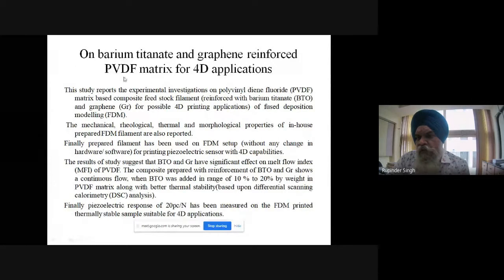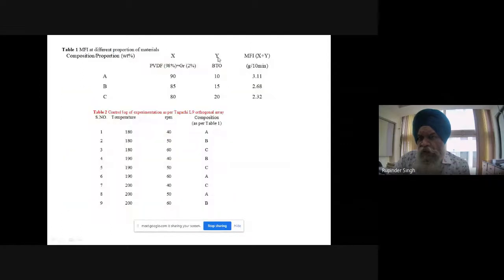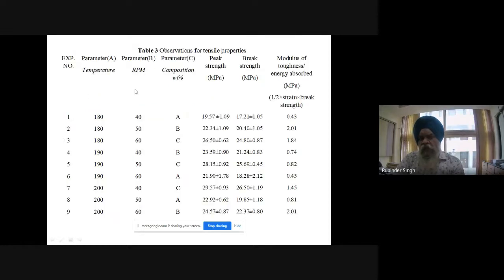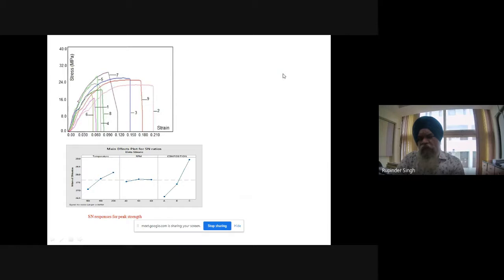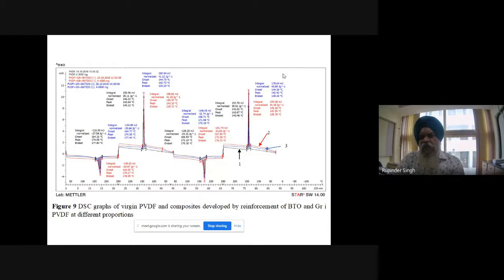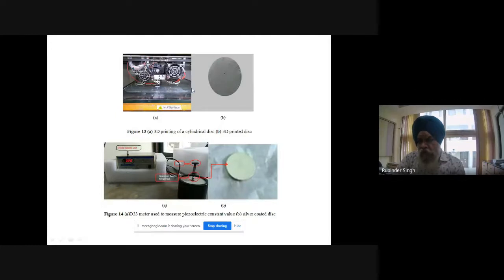We use a smart material, PVDF, and to increase its piezo property as a smart material, barium titanate and graphene were reinforced into it, right? So we tried initially with 98% PVDF, we put some graphene and some barium titanate into it. We did some parametric optimization, and we tried to see the effect on peak strength, break strength, modulus of toughness, the stress strain curves were observed, the thermal stability values were observed. Then we tried to print the component, and we tried to see what is the effect on the piezoelectric constant. So D33 was measured, and we were able to get around 20 picocoulomb per Newton. This is very good for the self-assembly application, right?